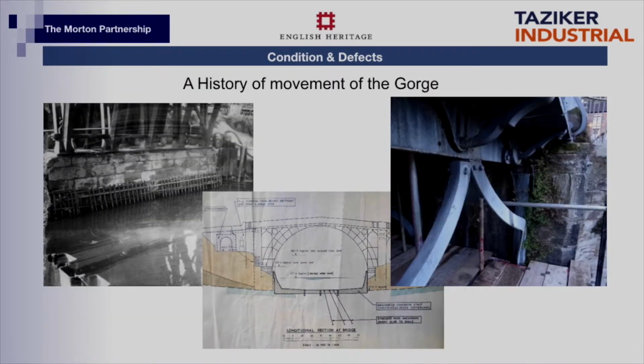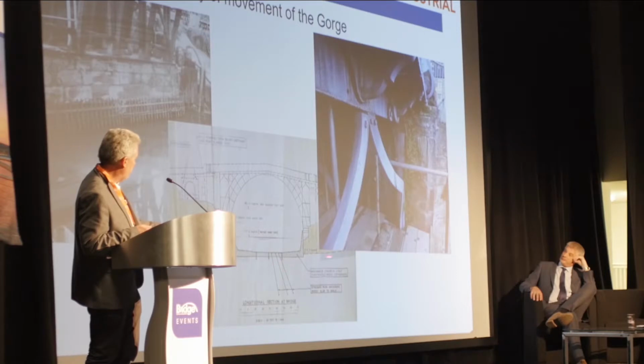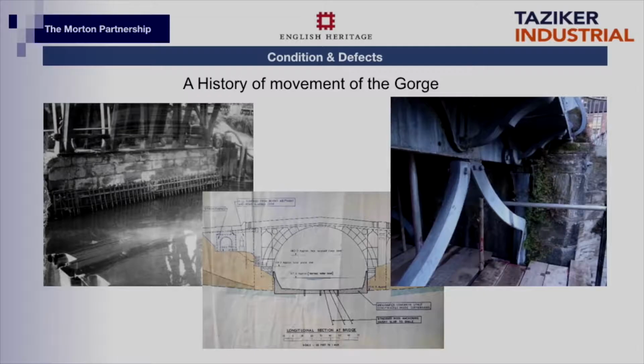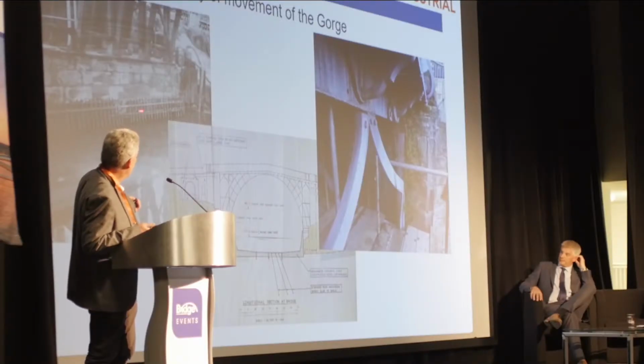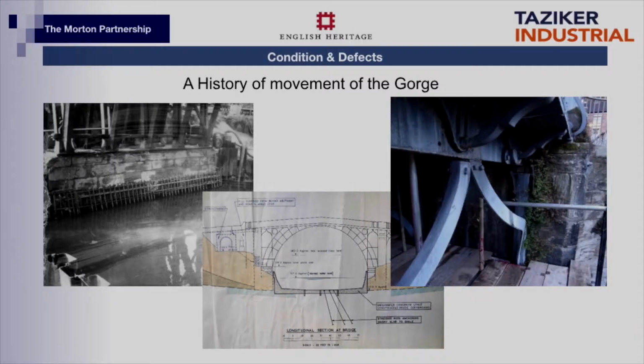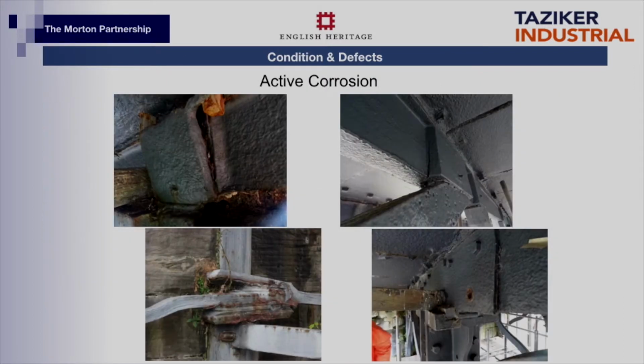So a few images. You can see our concrete strut that was put below. We had a diver survey carried out to check that that was still okay and there was no scouring around it. And that's a historic image of the reinforcement when they were creating it. And there we have a buckled OG arch to one edge. And here is the evidence of the corrosion.